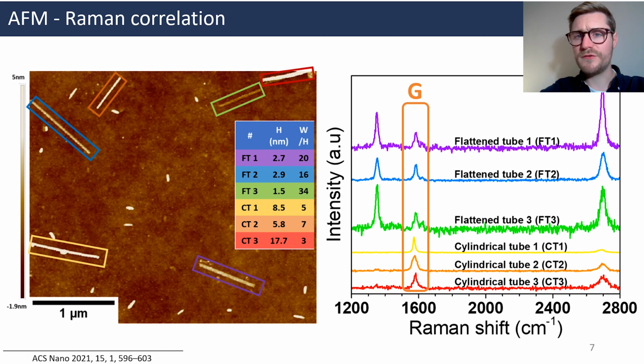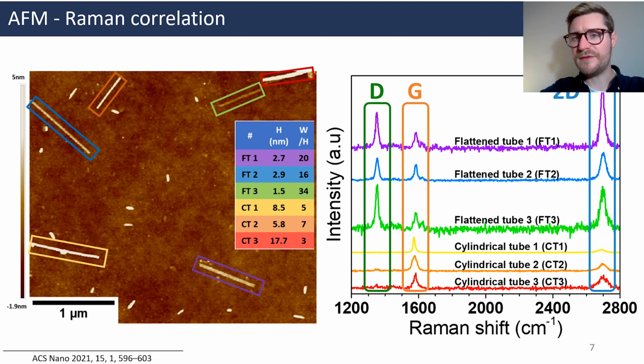A first difference that I won't have time to discuss is the 2D-band shapes and intensities. A second is the absence or quasi-absence of a D-band in the case of isolated cylindrical carbon nanotubes, while flattened tubes present an intense and narrow D-band. The absence of D-band in cylindrical tubes is telling us something really interesting here. It's saying that there is almost no structural defects in the cylindrical tubes and in the flattened tubes as well.